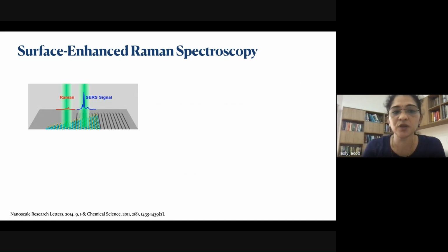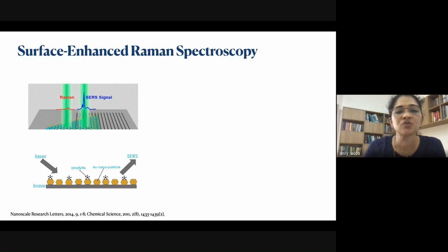Surface enhanced Raman spectroscopy, or surface enhanced Raman scattering, is a surface sensitive technique which enhances the Raman signal by the adsorbed particles on rough metal surfaces. This is a result of chemical enhancement and also electromagnetic enhancement. But the major contribution is from electromagnetic enhancement, and we are now focusing on that. So what happens is that when laser light falls on silver nanoparticles, surface plasmons get excited, and these surface plasmons produce an electric field enhancement in the vicinity of the nanoparticles. The analytes have a Raman scattering, and a re-radiated field will be produced, and they will combine together and result in a surface enhanced Raman signal.